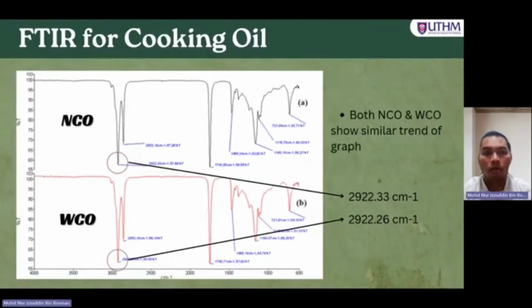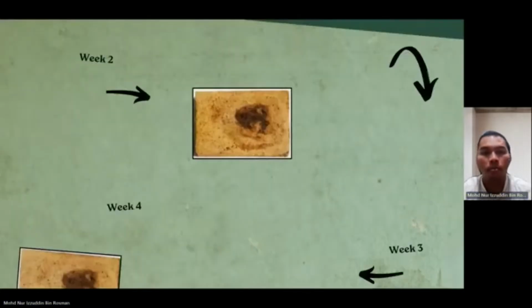But for the saponification value, the new cooking oil has 42.08 and used cooking oil has 28.05 milligram per gram. Okay, for the FTIR of the cooking oil, as you can see in the second part of the focus point, both new and used cooking oil show a similar trend in the graph, with a similar value of 2,922 per centimeter, which shows that both oils have similar properties.